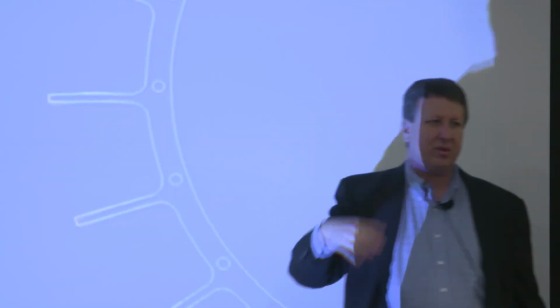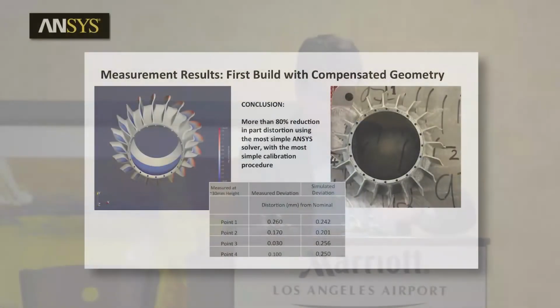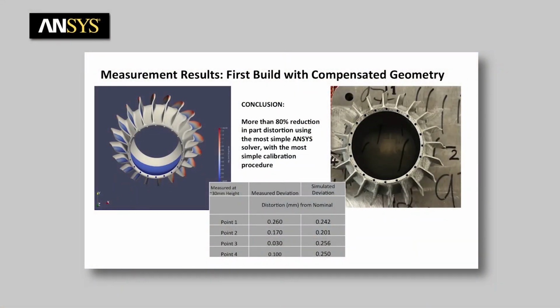Then we measured at a Z height of 30 millimeters and predicted that, hey, indeed, the distorted geometry is now going to line up pretty well. The distortion compensator should line up pretty well with the design. So we went there, and we measured it. We showed the prediction versus the measured. They were either better than predicted or quite good. But the main conclusion is that just with our most simple simulation type, we had an 80% reduction in distortion.